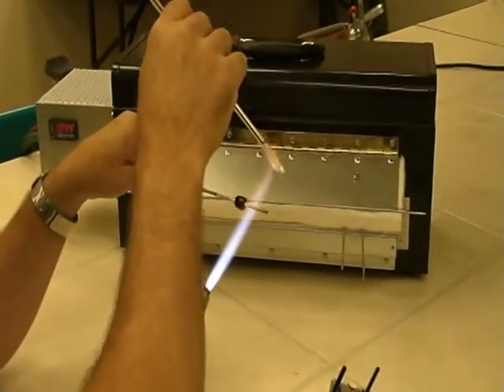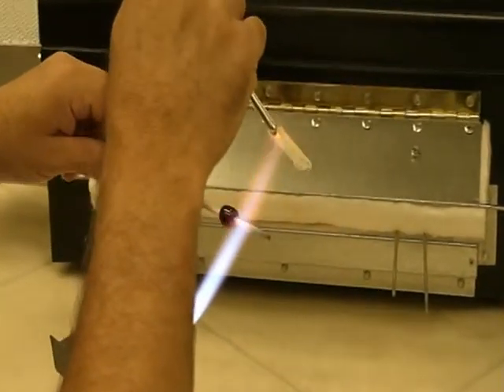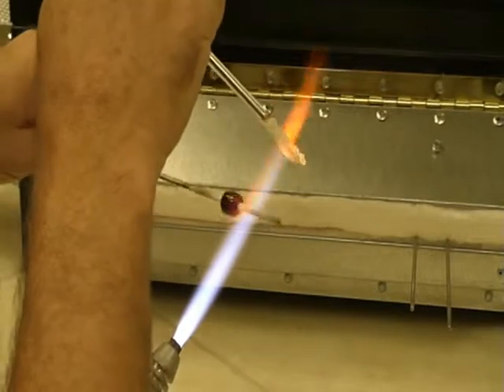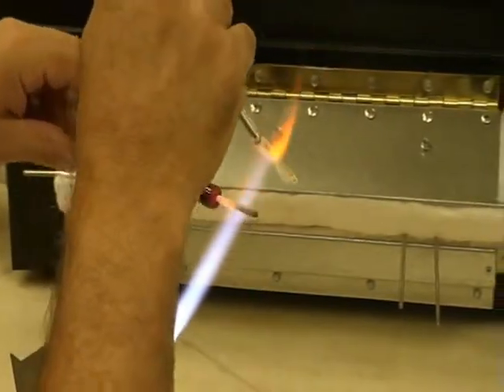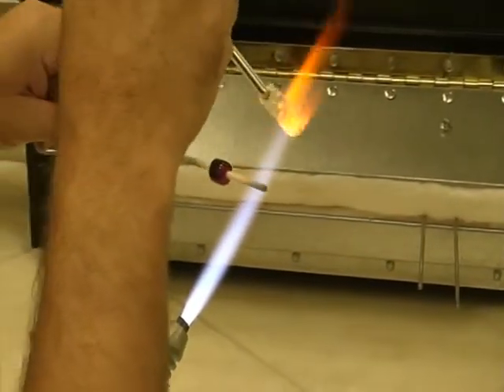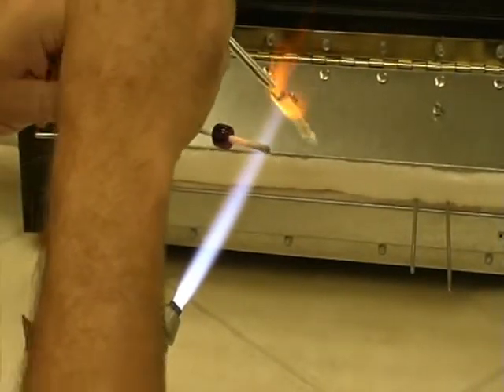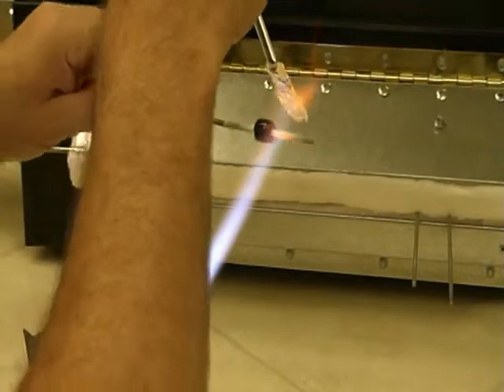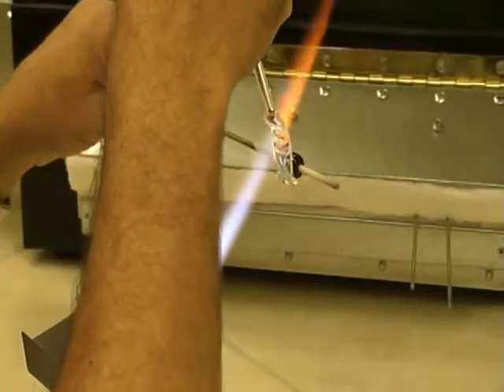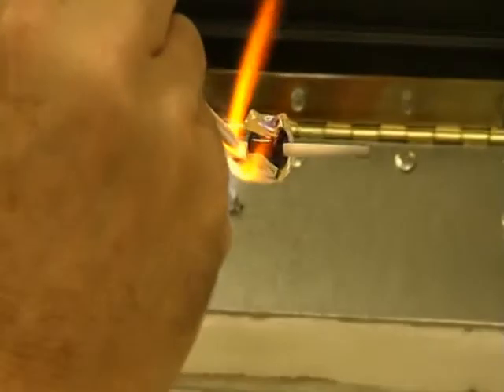I'm going to heat both sides of this strip. This is a fairly thick piece of glass. It's a ripple with rainbow dichroic. I'm going to keep my bead warm. Don't want it too hot. I don't want to deform the bead as I apply this. And just as my strip of dichroic starts to bend a little, right about there, I'll come out of the flame and touch the strip to my bead. Once it attaches, then I'll bring it back into the flame and heat the strip enough so I can wrap it all the way around the bead.